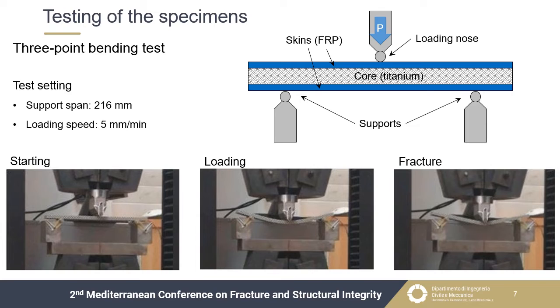The produced specimens were tested according to the ASTM C393. That is the standard for the evaluation of flexural behavior of sandwich structures. In fact, the flat specimen considered in this work can be assimilated to a sandwich structure. Indeed, the 3D printing is usually exploited for complex shaped parts, but a flat shape was chosen for this mechanical